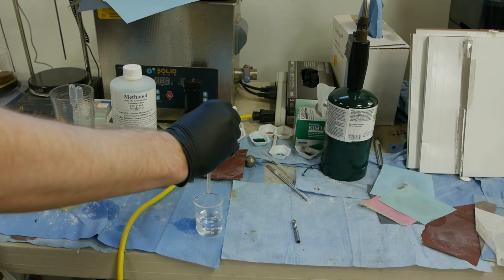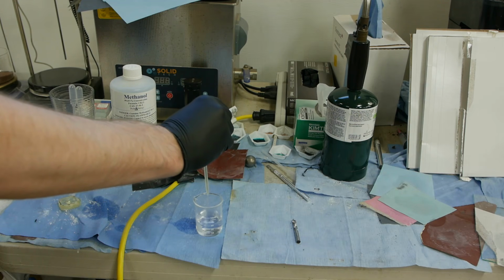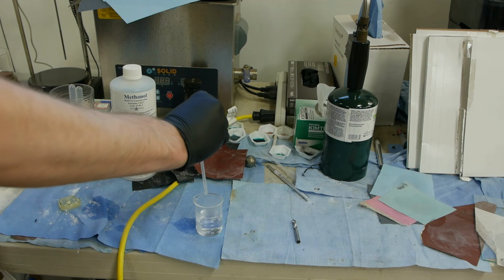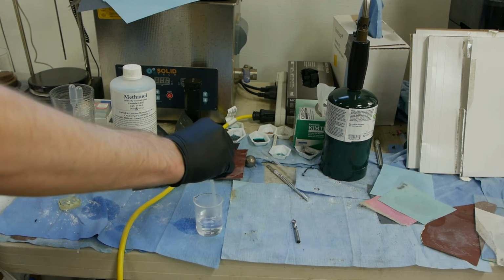The etching process is very quick. I used about 2 minutes to etch this tool steel, and that seemed to work just fine. For softer steels like low carbon steel, even 5 or 10 seconds in this 5% Nital is enough.